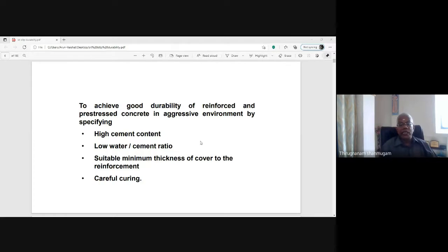And it gives in a tabular form the minimum cement content needed, the maximum water cement ratio, etc. So higher cement content depends upon the exposure condition. For mild exposure condition, it may be about 320 kg per meter cube. At the same time, for extreme severe condition, 360 or 380 kg per meter cube of cement. That is the minimum cement content you have to maintain.